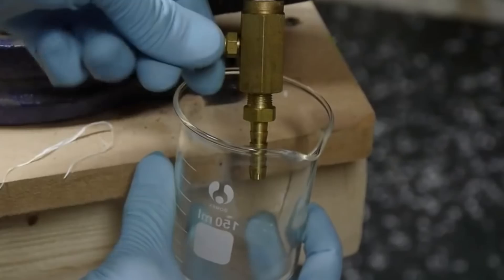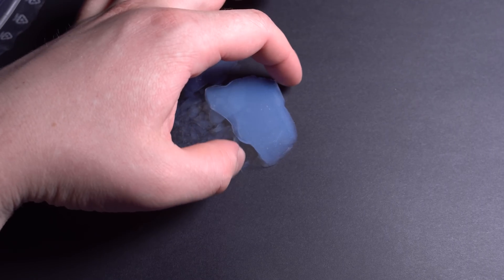Carbon dioxide is pumped under pressure into such an extractor. After that, the case of the extractor starts to heat up. The liquid carbon dioxide passes to the supercritical state, that is, becomes something between liquid and gas. In such a state, it can easily wash away methanol from gel, substituting it with gas. This is how aerogel forms.